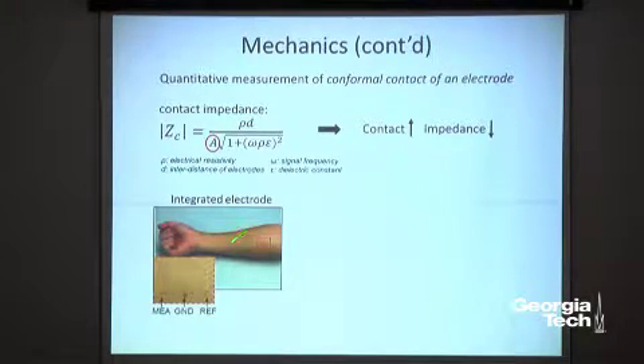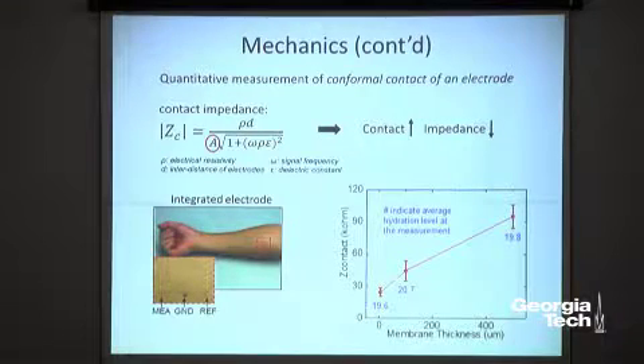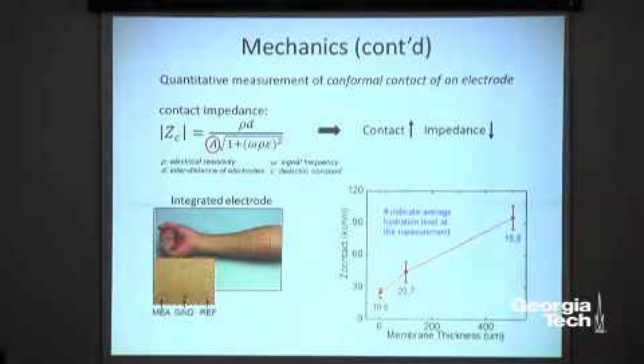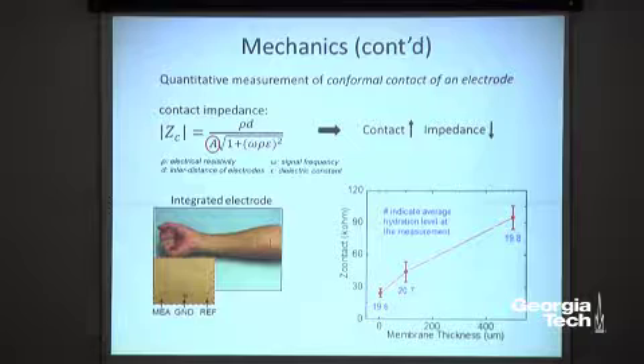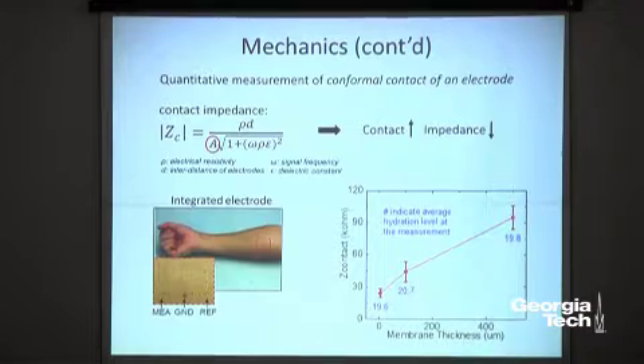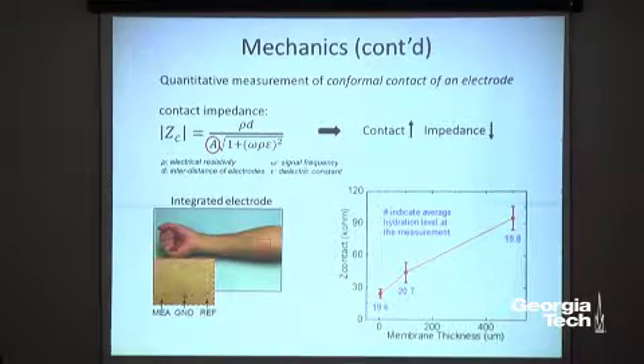So we put this electrode onto the skin and measure these impedance values. And as you see here, we started from 500 micrometers, and we reduced the thickness further and further down to 5 micrometers. And as you can see, with 5 micrometers, we have pretty low electrical impedance, about 20 kilo ohms compared to the thick membrane. So with this value, 20 kilo ohms, even without the gel, we can get nice quality of biopotentials from the skin. All right, that's how we can utilize the flexibility of material to design electrodes.